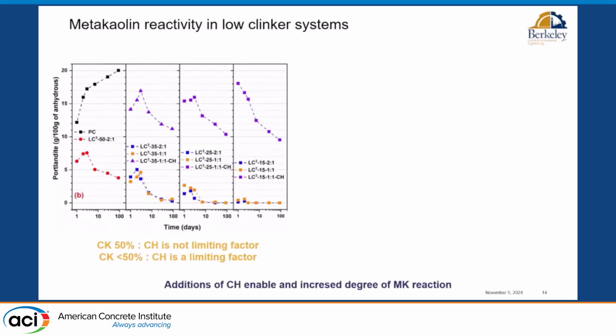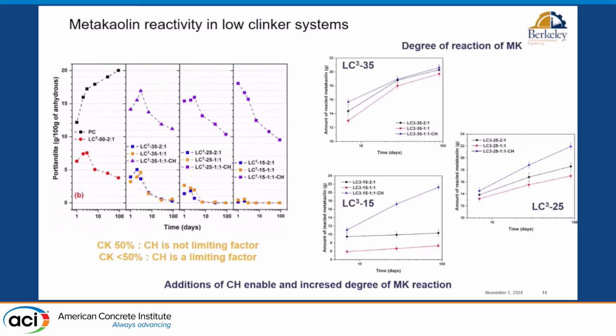We need lime, we need calcium hydroxide, reactive calcium to get this process going. And if you reduce the clinker factor too much, what happens is that you run out of calcium hydroxide very quickly in the process. Idea: what happens if we add calcium hydroxide on top of this as a doping agent? This doesn't make any sense from an environmental point of view, but from a chemistry point of view, what happens if we do that? So then we push the calcium hydroxide content up, and the advantage of doing that is that then we can sustain the metakaolin pozzolanic reaction even with clinker contents of as low as 15%.